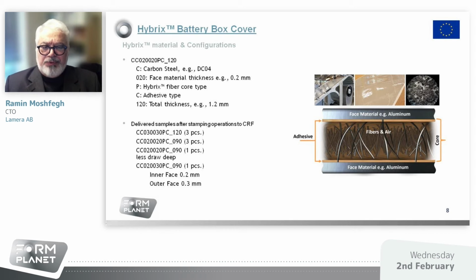For this purpose, we made different types of the sandwich material. We call it CC 0.2, 0.2 PC 120, and simply that tells us that this is carbon steel on both sides. The face material thickness is 0.2 millimeter. The core is the fiber core, especially for Hybrix. We have different types of adhesive systems. This is a C adhesive, and 120 means the total thickness is 1.2 millimeter. We made all those battery boxes based on those configurations, and sent those material samples directly to CRF in order to see if it's good enough or not.